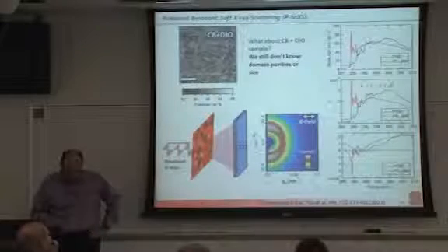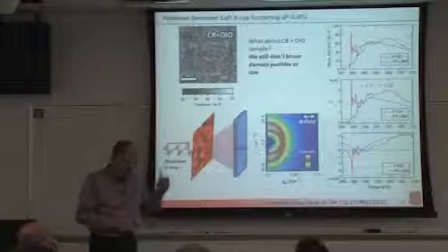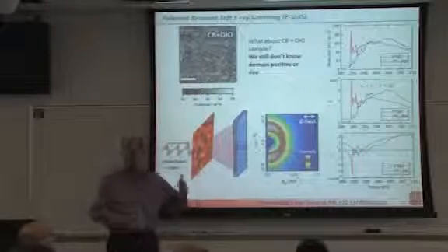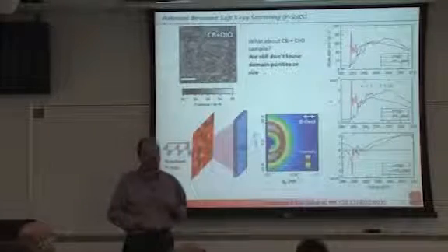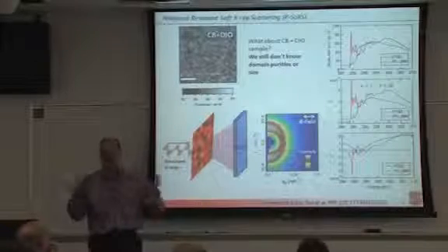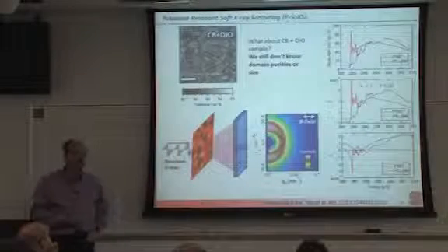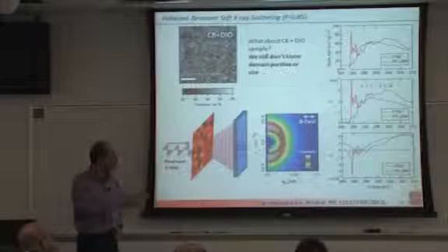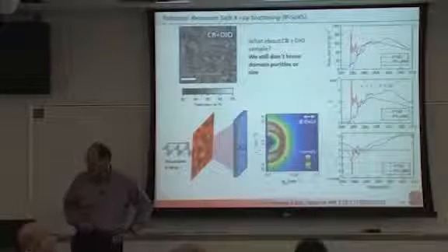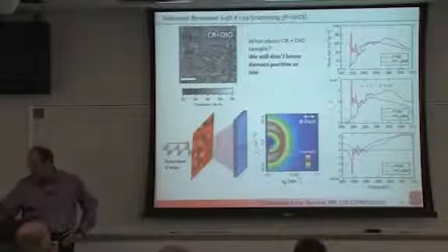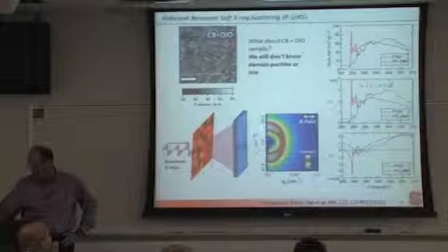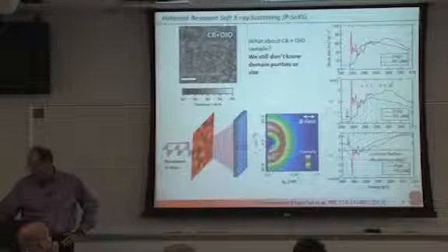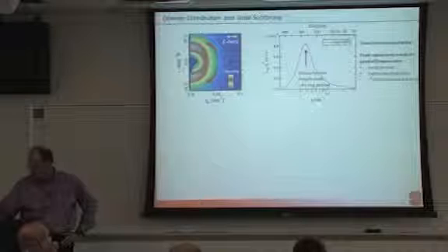And the scattering contrast is equal to the delta real part squared plus delta imaginary part squared. It's a delta n squared. It's the same as what you would have in the optical. So we can fully understand this materials contrast, and so we can use that to look at things.